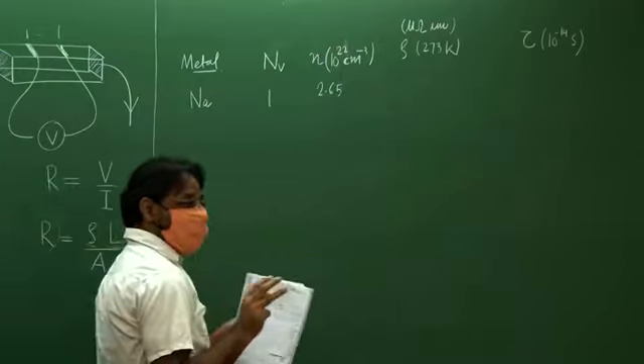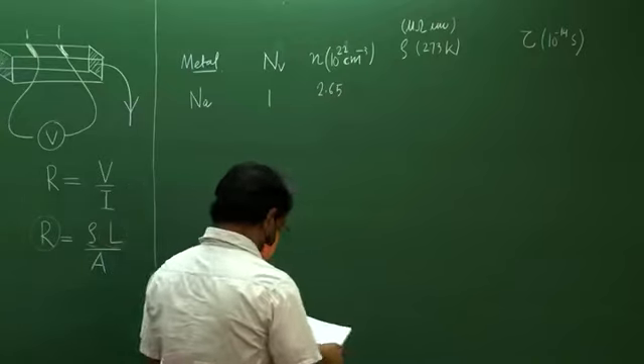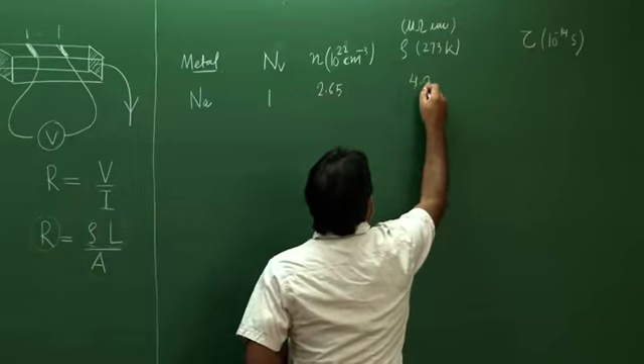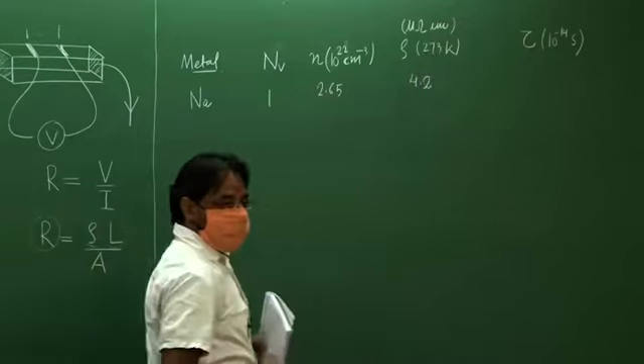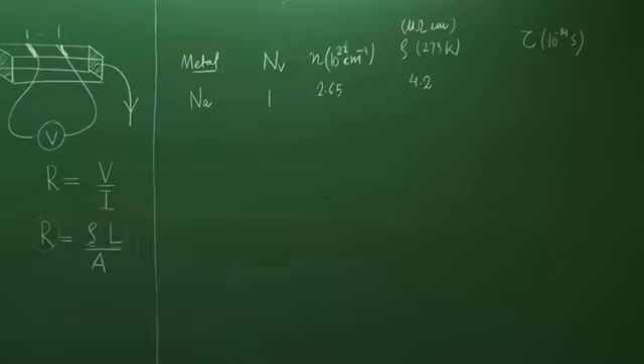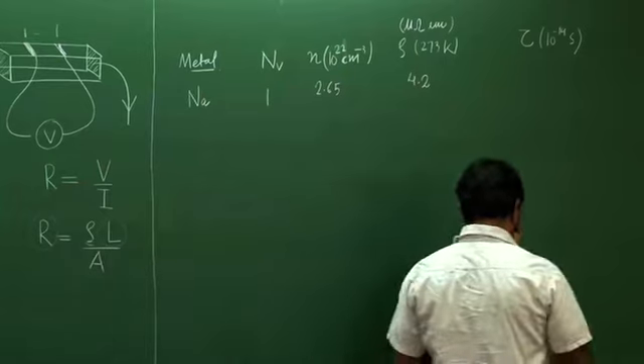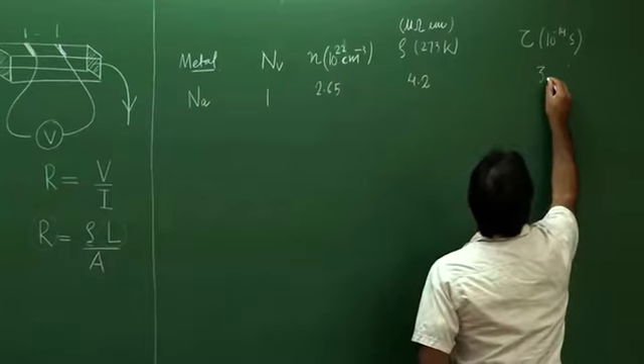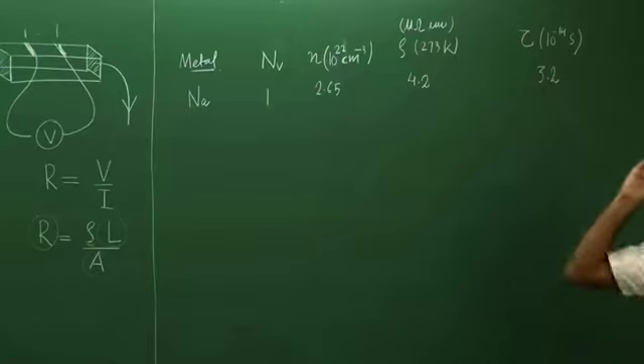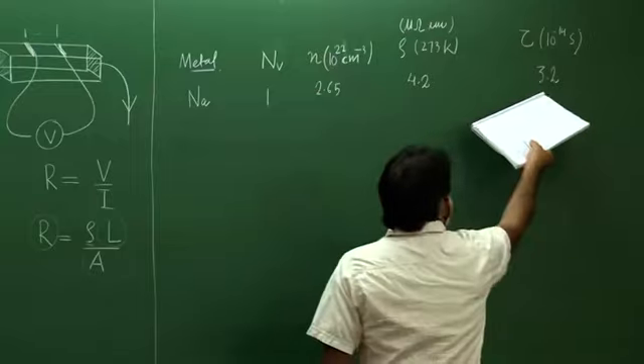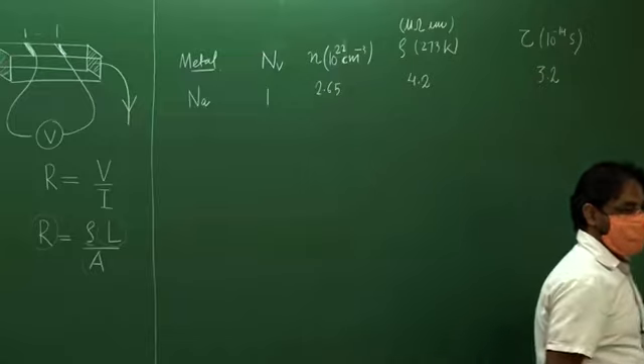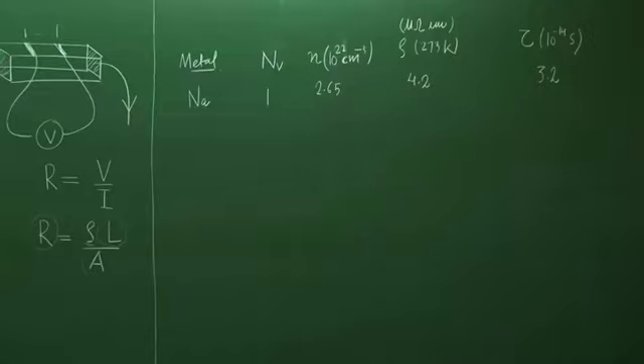So, the measured resistance, this is a measured quantity in the lab. This value for sodium is 4.2 micro ohm centimeter at 273 Kelvin. Now, you have the formula, you can get tau, and the value of tau comes out to be 3.2 into 10 to the power minus 14. Now, you may say, well, what do we know about this tau? That means 2 successive collisions happen as frequently as this, very, very fast. But we have no reference. How do we know whether this is right or wrong? It could have come out to be minus 9 or minus 8, right? At this moment, we have no reference. We cannot comment on the accuracy of that result, right?